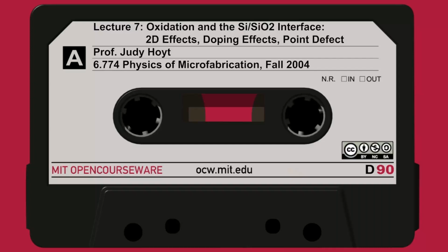Because we know even planar growth has some intrinsic stress during the oxide growth. The oxide is under a certain amount of stress even when it's planar. It's just under more stress when it's curved. But this stress can relax upon annealing at a high enough temperature, above 900, 950. The glass can flow a little bit, and the stress will relax. So when people measure the Deal-Grove linear and parabolic rate constants to describe oxidation in this intrinsic stress state, the 1D stresses are already accounted for. Okay, but let's look at the experiment that's shown on this slide.